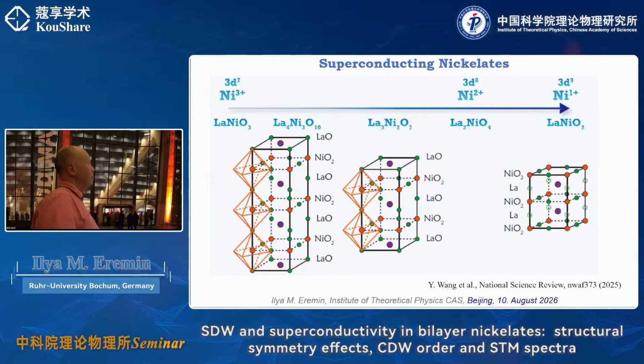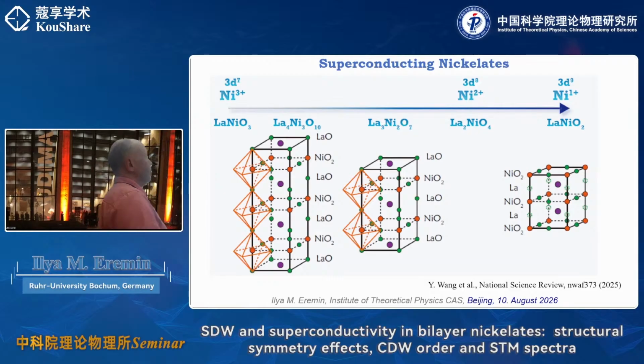if you compare the original motivation why people wanted to synthesize superconducting nickelate, that was a primary interest because, as you see, if your nickel has an oxidation of 1 plus, then the valence of the nickel ion will be 3d9. And that resembles very much the 3d9 of the copper oxides. The original prediction was that it should be a superconductor, but the difficulty is that to realize an infinite layer nickelate, which is this system, is very difficult and only succeeded in 2019. And meanwhile, we know they are superconducting.